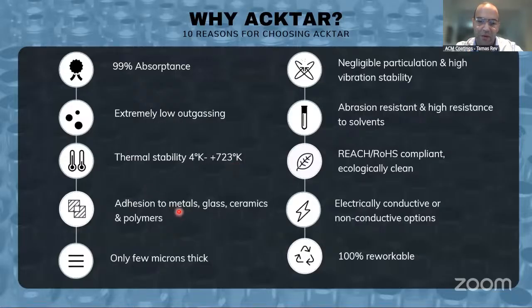We can literally coat any substrate. The most popular ones are metals, glass, ceramics, but we can also do polymers and composites. The limitation for our coatings is usually the lower temperature, so we cannot go below 80 degrees Celsius in our processes. And just to mention that all of our coatings are deposited in a vacuum chamber. As I mentioned, all of our coatings are very thin, they have negligible particulation, and they also have high vibration stability.